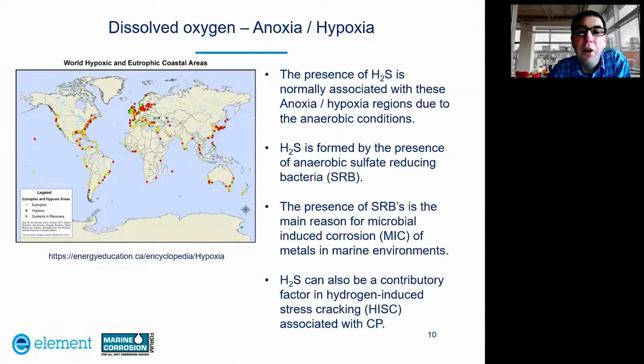Hydrogen sulfide is formed by the presence of anaerobic sulfate reducing bacteria, or SRB, and the presence of SRBs is a main reason for microbial induced corrosion of metals in marine environments. H2S can also be a contributory factor in hydrogen-induced stress cracking associated with CP, which I'll cover a bit later on in this presentation.